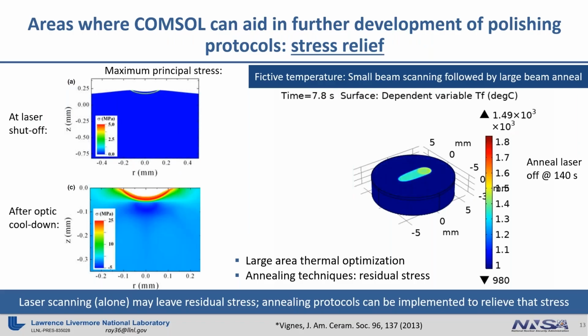We discussed densification, which is what's giving us our polishing depth. But you can imagine if there's densification, which will be dependent upon the fictive temperature, which will be a local effect, then there's going to be local densification. So there is definitely going to be some residual stress. And then the two plots on the left-hand side are from that Vignes paper, just to show the stress profiles. The top one is after laser exposure, like immediately after the laser was turned off, and then the bottom one is after the optic cooled back down to room temp. So we do see some residual stress.